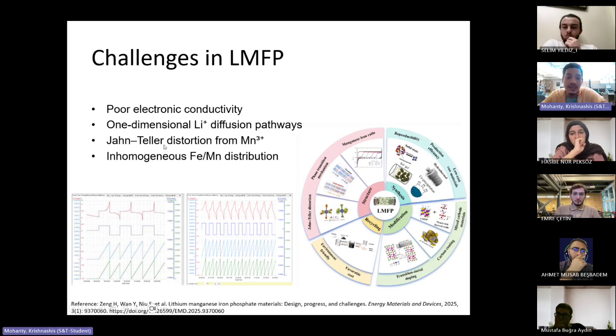And the last thing I would say, which is a challenge in LMFP, is the mixing of iron and manganese itself. When we have a ratio of two different materials being mixed in a solution, you want to have the right chemistry and right distribution of each and every ion within the lattice structure itself. Something as complicated as electrochemistry needs to have even distribution throughout the solution, or the electrode itself. Because even though we measure out the right amount of material or the precursor, it would not relate to the end product itself, or the end product could face polarization because of different concentration gradients throughout the structure of the battery.